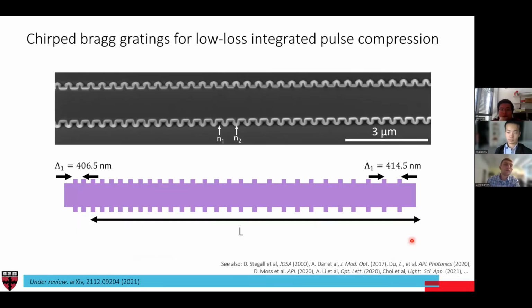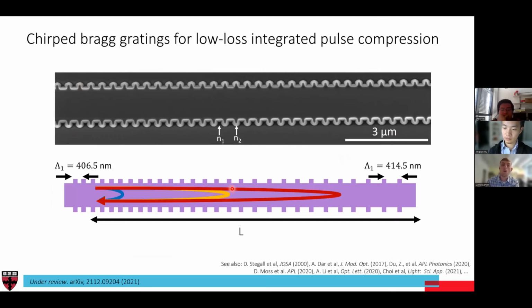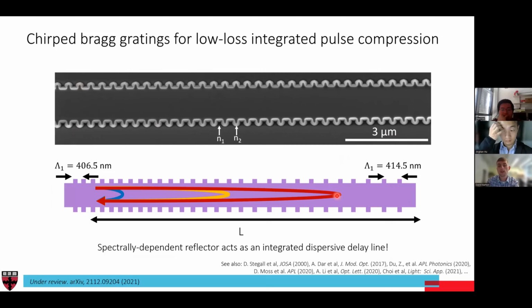And so what we ended up doing was making these chirped Bragg gratings. We basically have alternating layers of thick and thin waveguide that will reflect light at different positions. By changing the period of this, we can change the wavelength that's reflected in space. So maybe blue light will be reflected earlier on, then orange, and then red light would be reflected at different positions. And this allows us to have a spectrally dependent reflector that becomes a dispersive delay line.